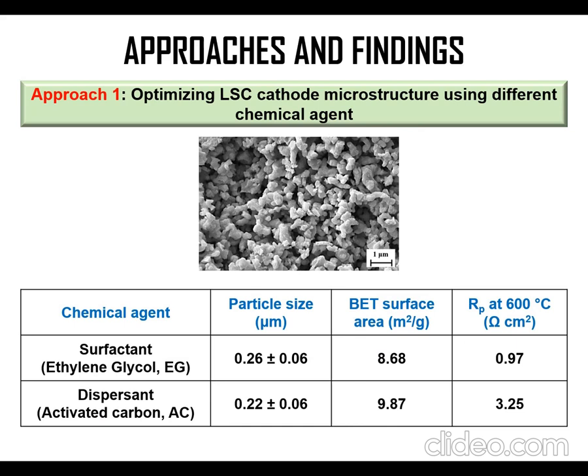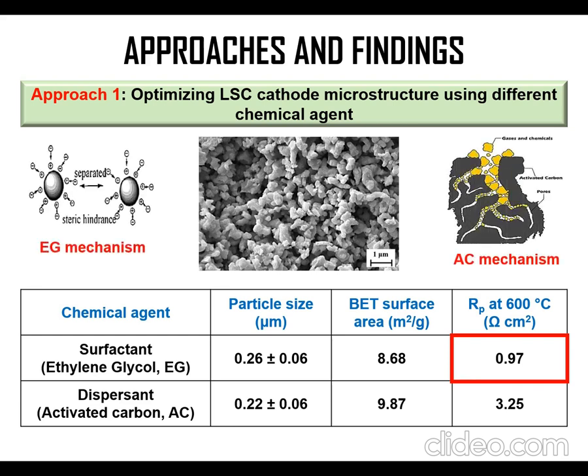Here are a few approaches we adopted in this work to reduce the RP value. Number one, we optimize the LSC cathode microstructure by using different chemical agents. The lowest RP was recorded when we used surfactant as the chemical agent. Different chemical agents have different mechanisms and will affect the properties of the LSC cathode produced.